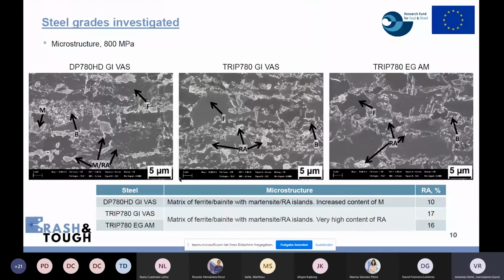Here you can see SEM images of the grades with 800 megapascal. I would like to give you some information about the microstructure for the grades investigated. The DP780HD high ductility grade had a matrix of ferrite and bainite with some martensite retained austenite islands. When compared to the TRIP steels, this dual phase high ductility grade had an increased content of martensite and lower retained austenite content. And both TRIP steels had a matrix of ferrite and bainite with martensite retained austenite islands and very high content of retained austenite.